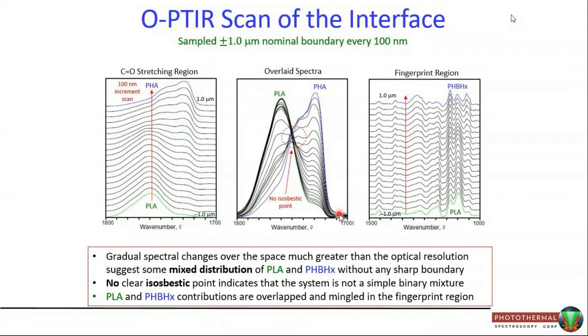That means this laminate system is not a simple binary composite, because if so, there should be an isosbestic point, but there's a lot more complex interplay of the different components within PLA and PHA. Fingerprint region also shows the gradual change. This area is a lot more congested, maybe more complex.